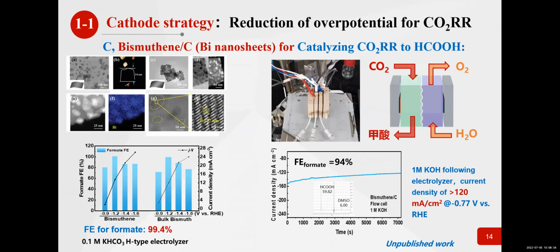Also, most recently, we synthesized bismuth nanosheet as a catalyst for catalyzing the carbon dioxide reactions. This material also shows a high Faraday efficiency for formic acid formation, above 99%. And if we set up an electrolyzer, at the anode we can produce oxygen, and at the cathode the carbon dioxide can be reduced to formate or formic acid. The Faraday efficiency in this electrolyzer is about 94%.